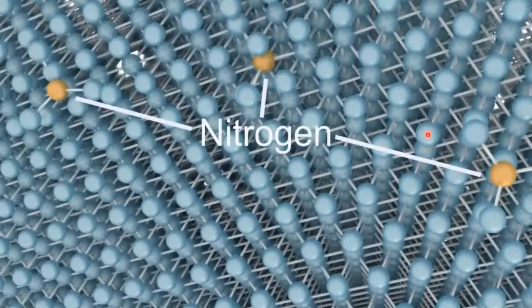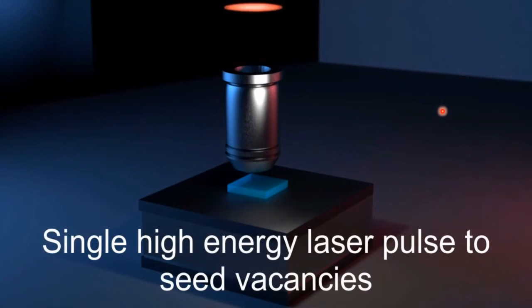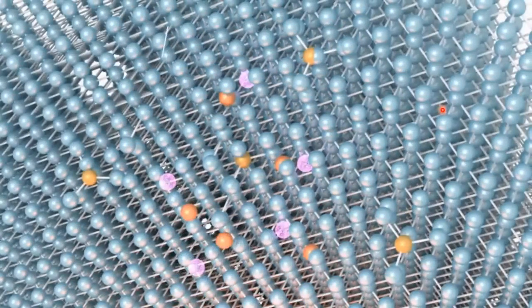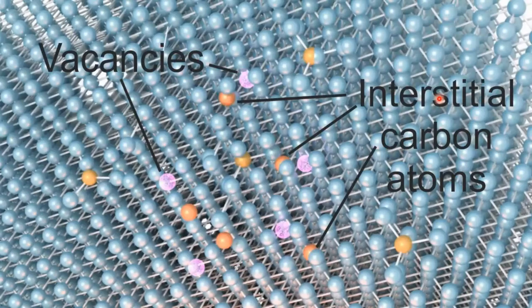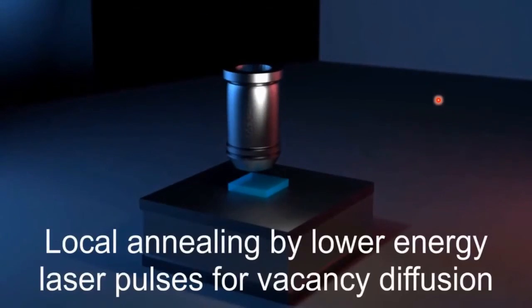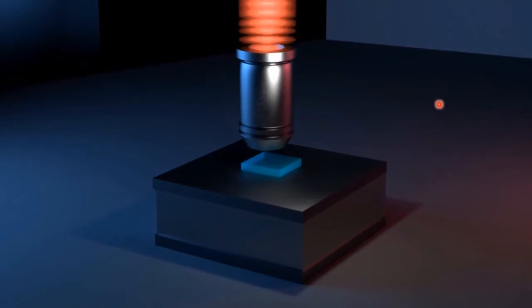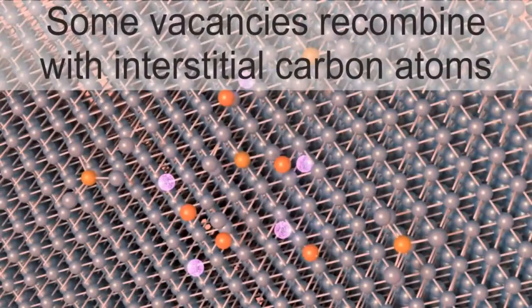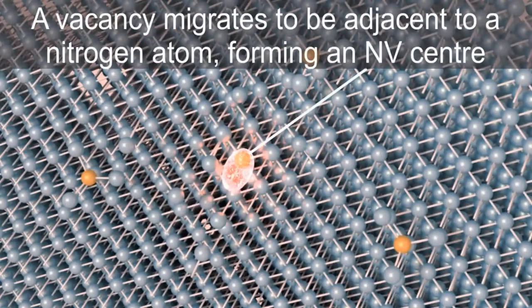And this will allow us to watch for fluorescence appearing as we're performing the annealing step in our diamond. So this video illustrates what's happening during this process. In the diamond lattice, we have some nitrogen, and this is quite highly doped with nitrogen to about 2 parts per million. And then we apply our first high energy laser pulse to create vacancies. And this actually creates Frenkel defects, so it creates vacancies, but also creates interstitial carbon atoms. And then we turn down the laser pulse energy and apply this 1 kilohertz stream of lower energy annealing pulses. And this just puts enough energy into the diamond lattice to gently anneal the diamond and mobilize both the interstitials and the vacancies, some of which will recombine with each other, but then eventually a vacancy is likely to find a nitrogen and form a stable NV complex.